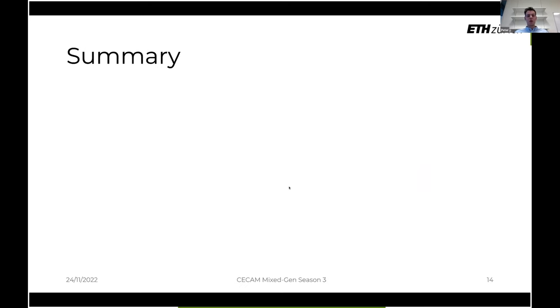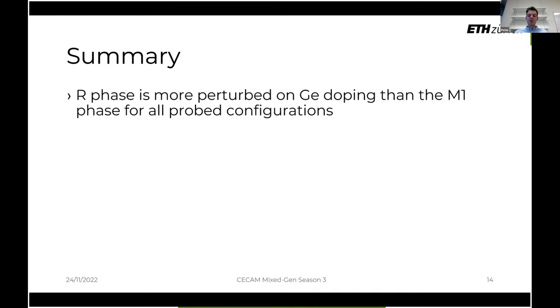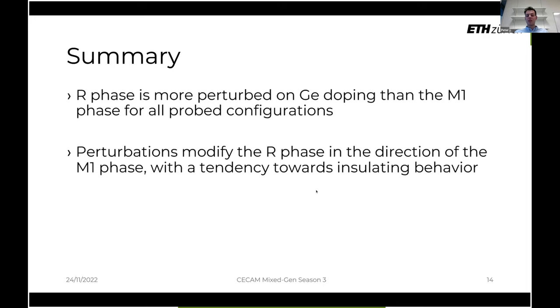And indeed, this brings me to the summary and the conclusions. At first, the first thing to note is that under germanium doping, the rutile phase is much more perturbed than the monoclinic phase for all the different configurations that we probe. We also see that these perturbations seem to take this rutile phase and bring it closer to the monoclinic one, both from the structural standpoint and, leading on from it, also from the electronic standpoint. We observe that this rutile phase starts to form structural dimers, which then lead to electron dimers.